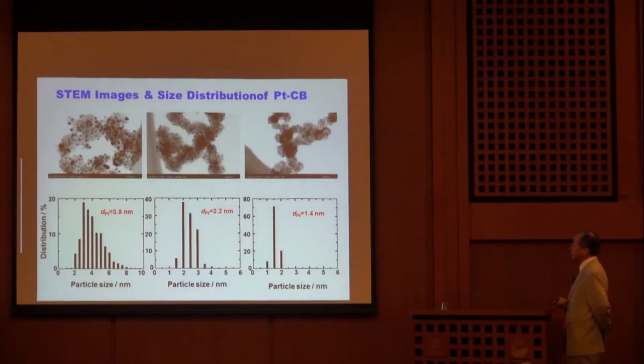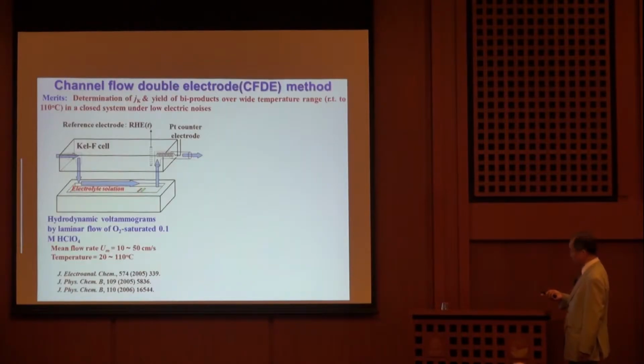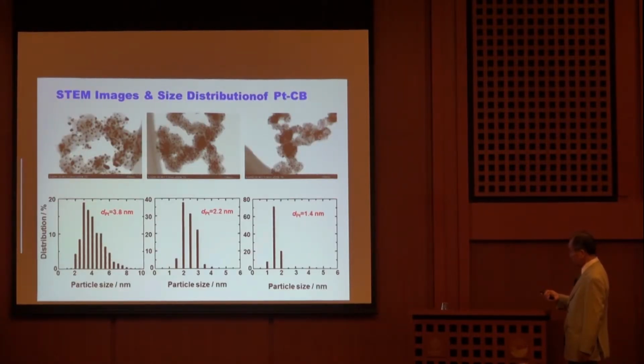So here shows the electrocatalyst which was used for the experiment. Here shows the three types of catalyst which have different particle size, about 1.4, 2.2, or 3.8 nanometers, or some other catalyst, which shows the size distribution shown here.